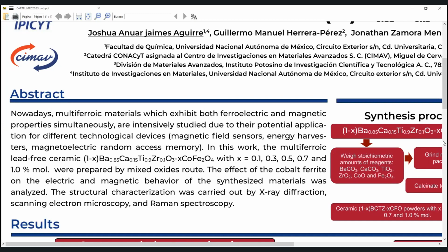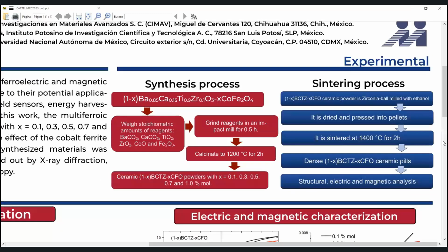of the ceramics. To carry out the synthesis of the ceramics, stoichiometric amounts of the precursor oxides and carbonates were weighed. Later, they were ground and mixed in an impact mill to later give them a heat treatment at 1200 Celsius, with a respective previous decarbonation process. In this way, ceramic powders were obtained, which were subject to a sintering process where they were ground with ethanol in a planetary mill. After drying the powders, pellets were made with a hydraulic press, and these were sintered at 1400 Celsius. The pellets obtained were used for structural, electrical, and magnetic analysis.